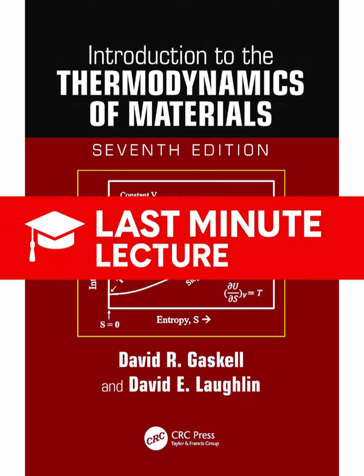So if we assume S is zero, what are the physical consequences? What does that mean for the ground state of a material? It imposes incredibly strict conditions. For entropy to be zero, the system can only have one possible quantum mechanical microstate. Perfect order. Perfect order. This means stable phases at absolute zero must have zero configurational entropy.